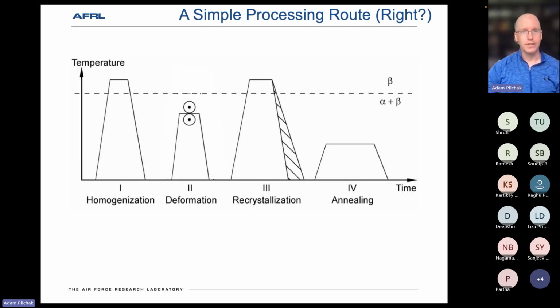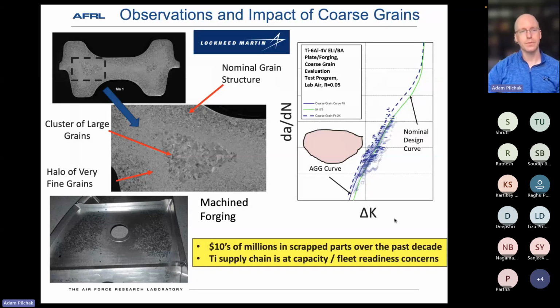So very simple. Been doing it for decades, yet sometimes, very periodically, when cut-ups are performed, you'll find these large clusters of really coarse grains. And so showing a cross-section from an actual structural forging there, and at a little higher mag in the inside, you can see this big region of really large grains, so large prior beta grains, and then they have correspondingly very large alpha colonies within there.